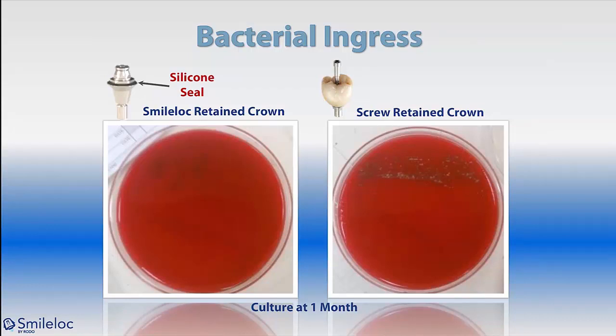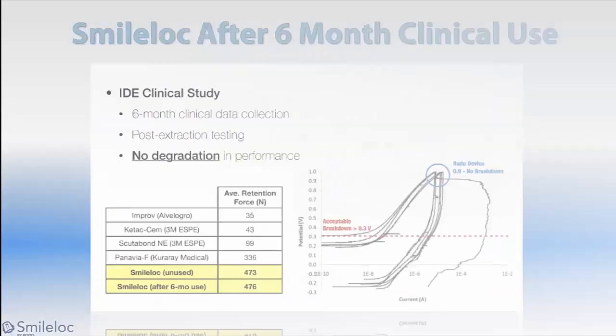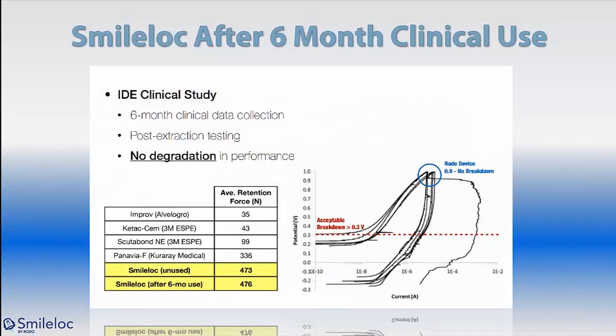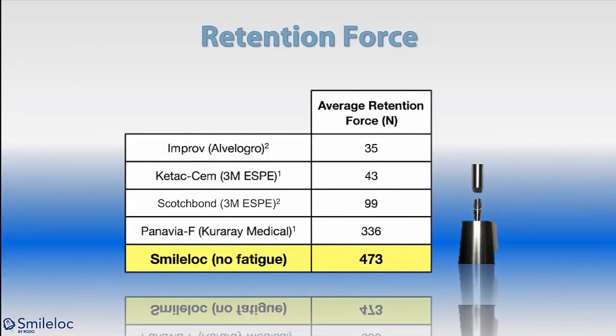Smile Lock, as you can see because of the silicone seal, no bacterial growth. Screw retained on the right after 1 month, had bacterial growth. Smile Lock system after 6 months of clinical use, there was no degradation in performance of a used Smile Lock compared to a new Smile Lock. Retention forces also were greater than Panavia, Scotch Bond, Ketac-Cem, and Improv.